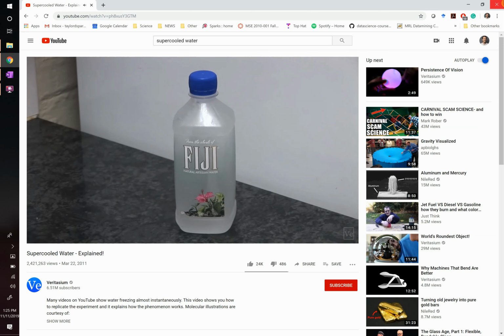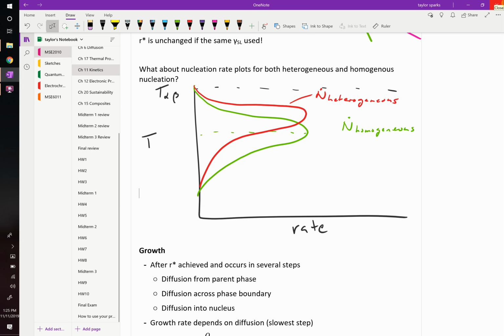At no point was it not thermodynamically favorable for that to happen. It's just that it had that surface energy that it couldn't quite overcome. So little ice particles were forming, and then they were dissolving again because it didn't have enough to get over that hump. But as soon as you gave it something to get it started, you could actually measure the rate at which it transforms, right?